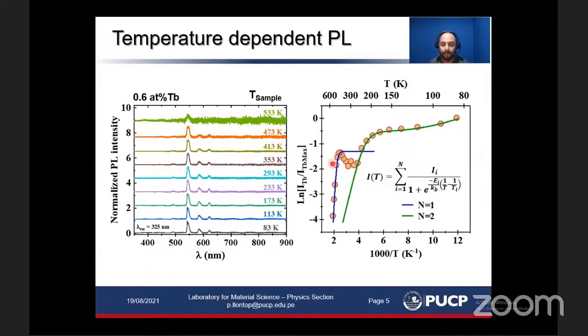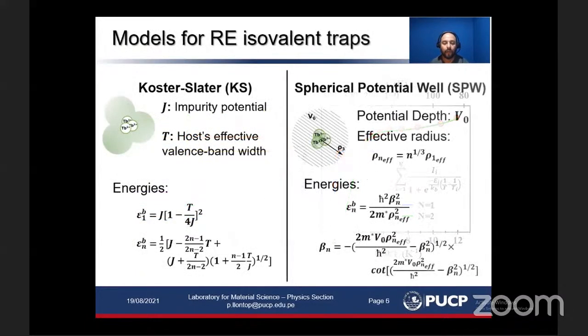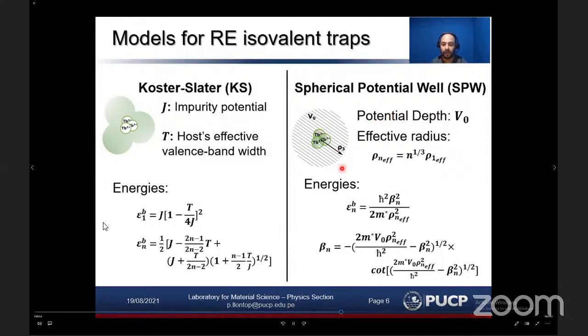So we use 2 models for this kind of cluster traps, rare isovalent traps, the Koster-Slater model and the spherical potential well model. In the Koster-Slater model, we have 2 parameters to be calculated, the impurity potential and the host effective valence bandwidth. And these are the expressions to calculate the binding energies. In the case of the spherical potential well model, there is a potential depth, which is the same regardless of the number of ions inside the cluster, and the effective radius. So with this, we can calculate the binding energies corresponding to this model.